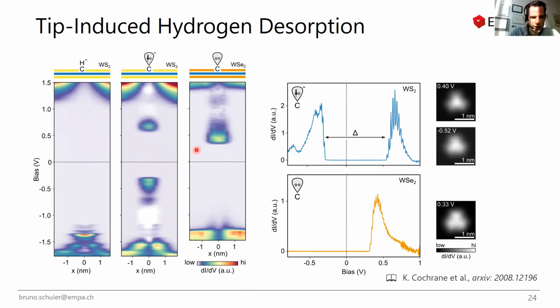And then if you look at a cross section here, so just at a single spectrum, we see the same thing. And there is even a more sophisticated subband structure here. So there is this equidistant peak, which we in fact assign to vibronic sidebands of these electronic states. And if you map them out in the negative and positive bias, you see that they look fairly similar. So we attribute this to a singly occupied defect orbital. So we can call this a negatively charged carbon radical.